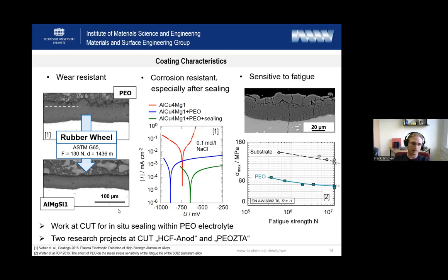We have received funding for 2 research projects. One is HCF anode. In this project, we focus on the interaction of the PEO process parameters, the created residual stresses, and the resulting fatigue behavior. And we now just start another research project where we focus on reinforcing the created aluminum oxide coating with zirconium oxide to get a composite ceramic material with an elevated fracture toughness. So we want to stop the formation of cracks inside the coating and so improve the fatigue behavior of these components.